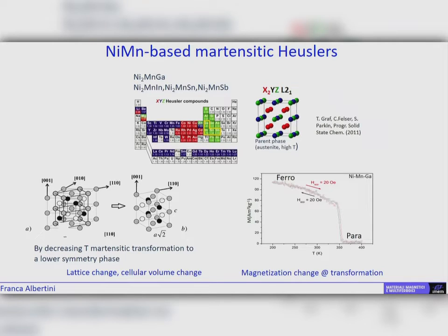And we have a huge change of magnetization of these materials that can be tuned at different temperatures. Indeed, these materials are very nice and flexible because we can make many compounds by changing the relative composition between the elements and also by making possible substitutions. In fact, for instance, here you can see a first Martensitic transformation from the two phases followed by the Curie transition. By changing composition, we can merge the two transitions, and also by changing the elements, we can have different kinds of transition.